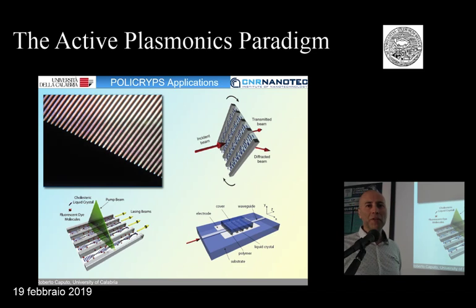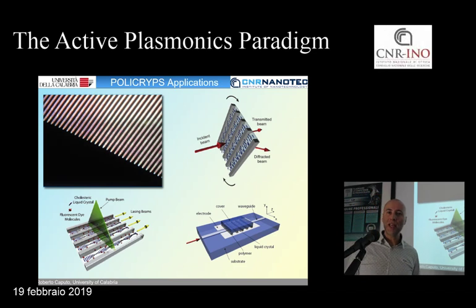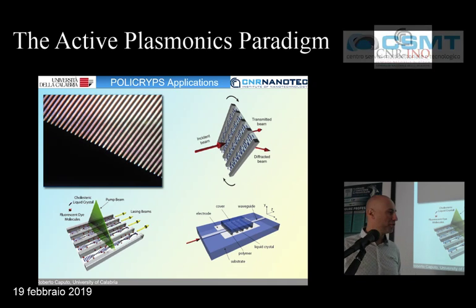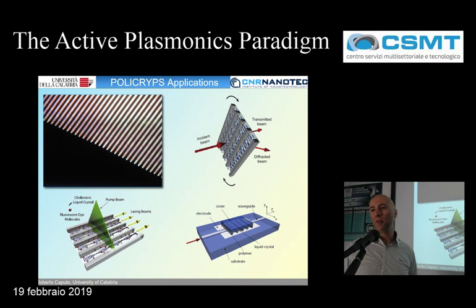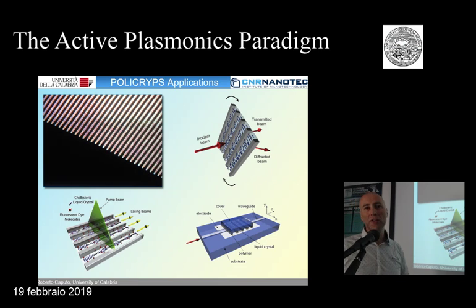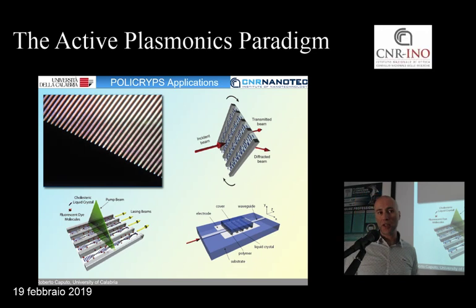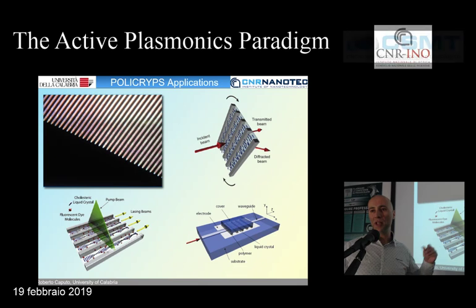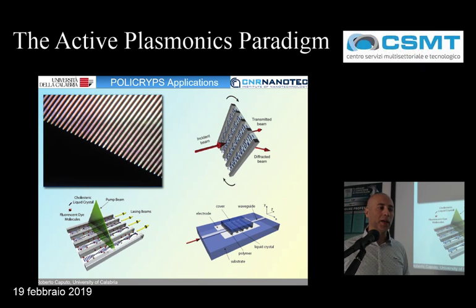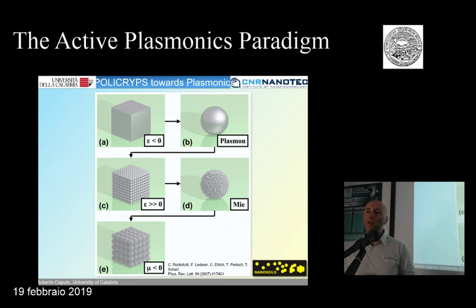And this is quite relevant because we tried to make a micro laser emission from a diffraction grating by using a particular kind of liquid crystal, which is a cholesteric liquid crystal, doped with fluorophores, with dye molecules. So in principle, by pumping this structure with a green laser, you can obtain lasing emission from each channel of the structure. This is quite relevant because also in this case, you can tune the color of the single channel, and you can even control single channels separately.